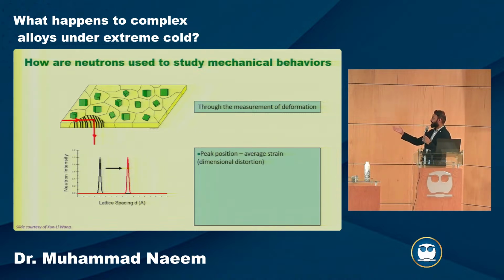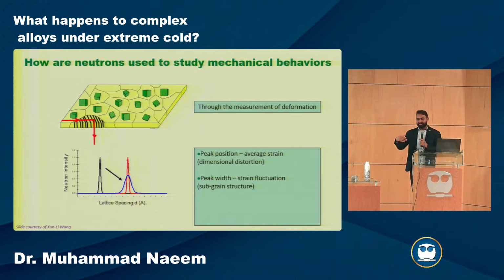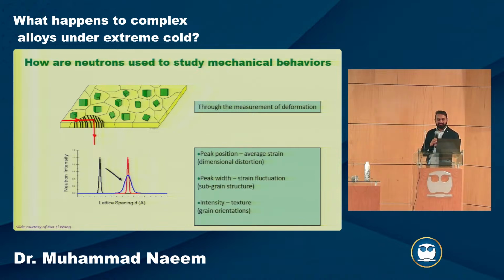This can happen because of the average strain in the material, because your lattice is being stretched now, right? So it's that distortion. Then it can also become broader. That can tell us something about its subgrain structure. For example, dislocations are generated, dislocation density is increasing, or certain other things, for example stacking faults or twins as well. Then we also have intensity. You see that the intensity has now decreased for this blue peak, which is about texture, how the grains are rotating in different orientations.